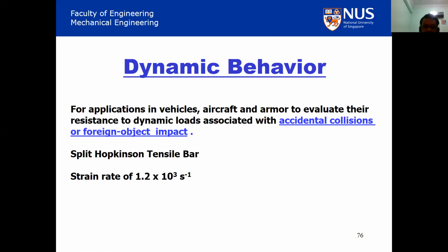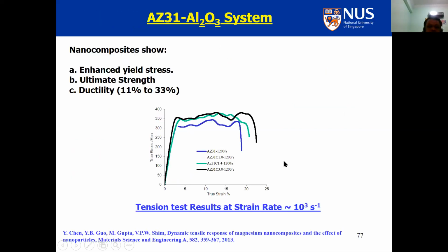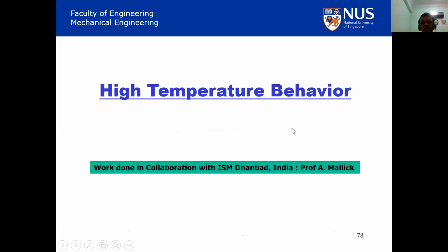Dynamic behavior is something used by transportation companies like the car manufacturers. In the case of collisions or accidents, you are exposed to loading at a high strain rate. That means your load is applied in a very short period of time. So I did some work with my colleague who was an expert in using the split Hopkinson bar, and I will show you this graph. Only see the blue curve here, which is the stress-strain response in dynamic loading for AZ31, not pure magnesium, and the black curve, which is a nanocomposite using Al2O3 particles. And you see that under dynamic loading, the nanocomposite shows higher strength levels and also higher ductility. So it's again good news for the auto sector.